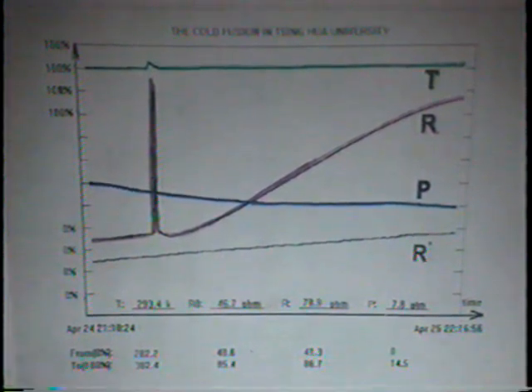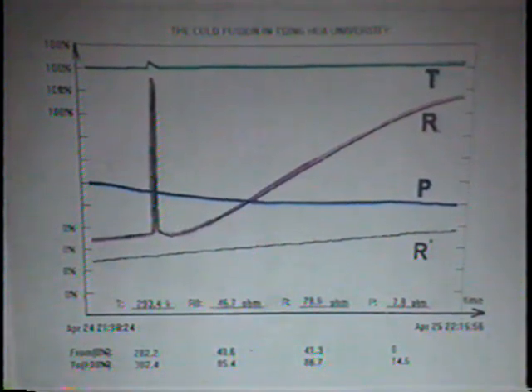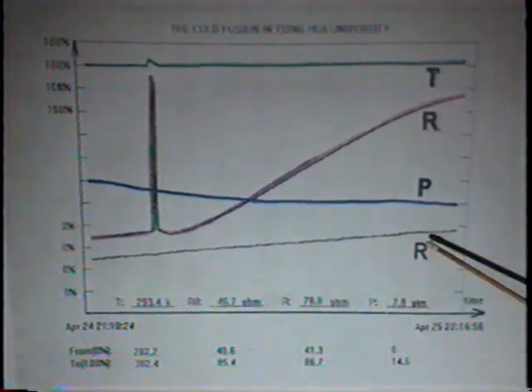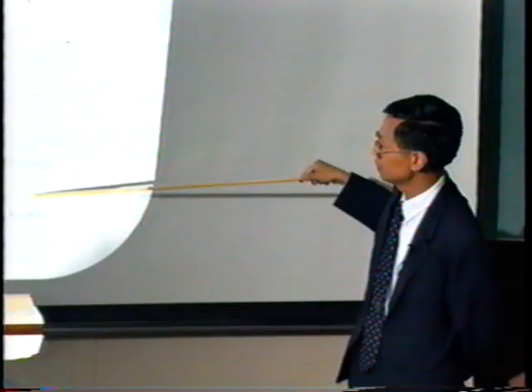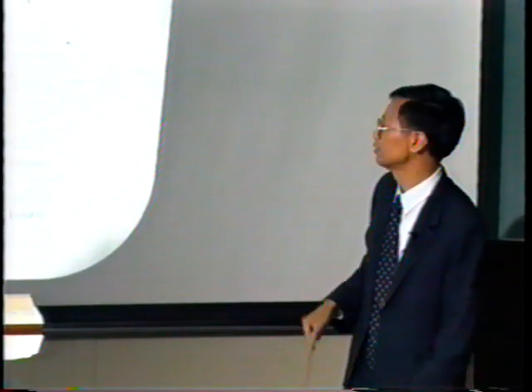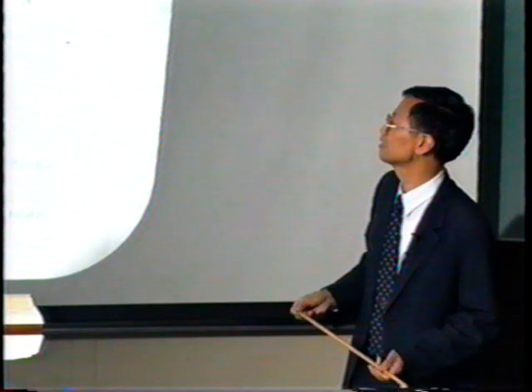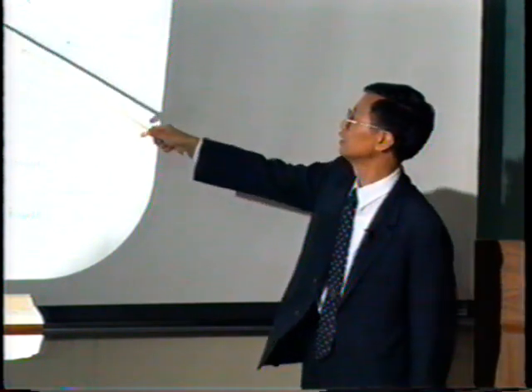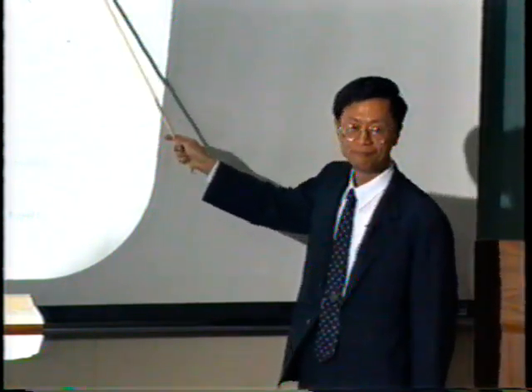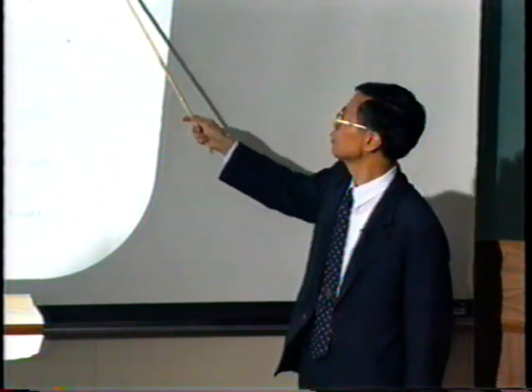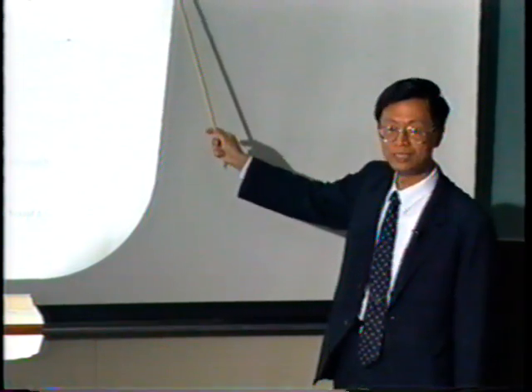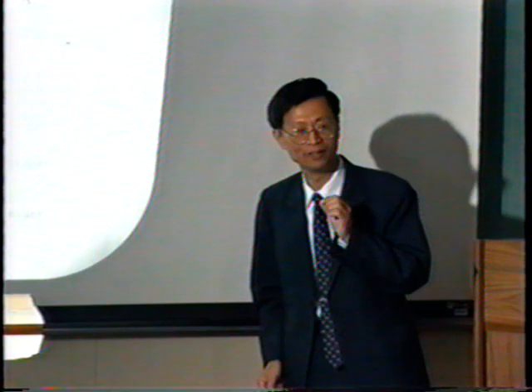As a comparison, after the pulse heating, we obtained the rate is 4.5% every hour, but this one is 0.3% per hour. So this effect seems very good for increasing the loading rate, but we later found this one will not reach the point we need. It affects the loading rate, but will not affect the terminal loading ratio.